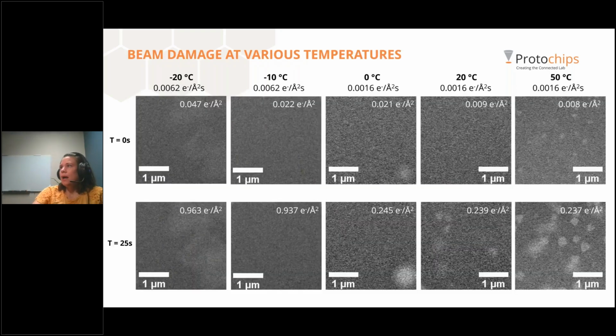So one of the things that we thought was very interesting while we were actually doing the experiment was that as we got colder and colder, it seemed like the amount of beam-induced precipitation that was occurring was decreasing. And we could go to higher and higher dose rates, meaning that we could actually have better resolution images because we were increasing our electron dose, that we could go higher and higher without seeing that beam-induced irradiation. Well, I wanted to actually pull that out of the data and see if that was true, right?